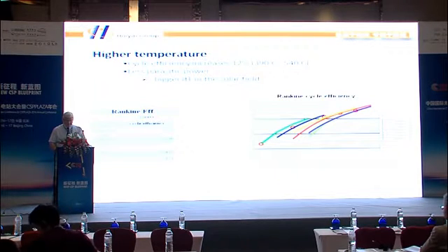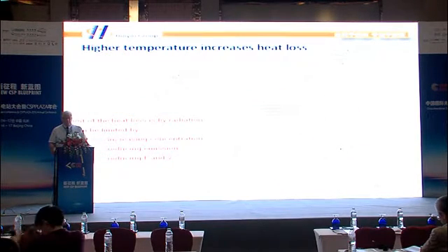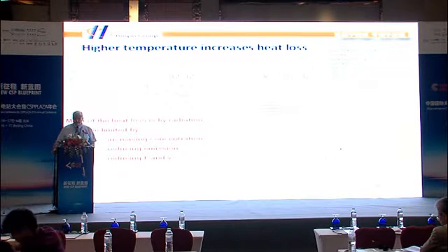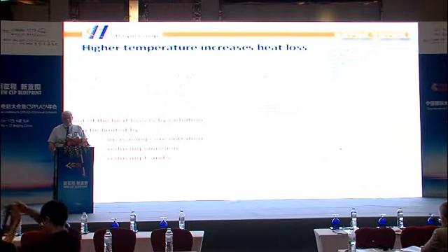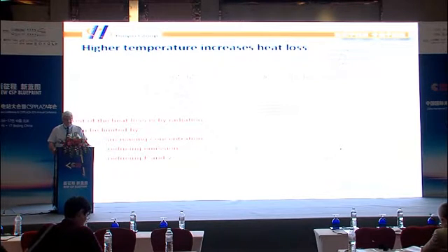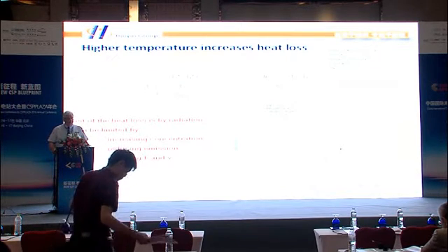Of course, with higher temperature comes also a higher heat loss. And here is the formula completely written out of what this heat loss is. And it contains several important parts. It contains the radiation level, of course. It contains the concentration, and it contains the emissivity of the glass tube and, of course, of the steel tube. And it contains a factor which is the conduction losses in the vacuum system.